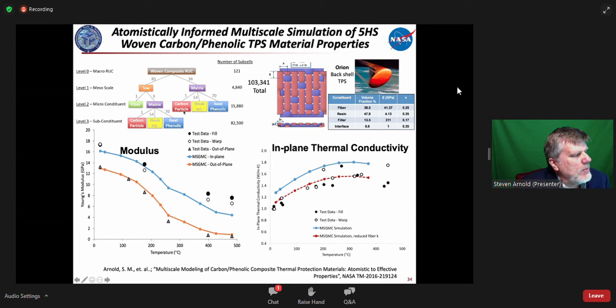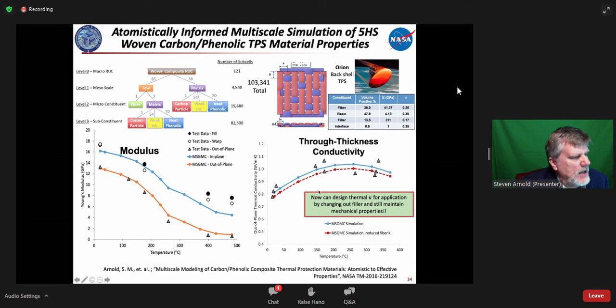And what was interesting here is we actually used first principle results for the properties of the various constituents, and then looked at a fairly detailed RUC, and we were able to predict the modulus for both in-plane and out-of-plane quite reasonably relative to the experiments over the full temperature range of 500 degrees here. And we're also able to predict the in-plane thermal conductivity and the through-thickness conductivity as well.